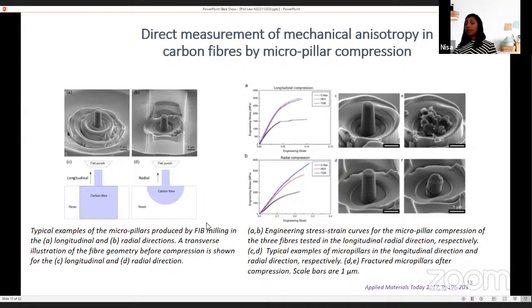So we have conducted these studies on 3 different carbon fibers with various modulus. We found that tensile stiffness was significantly higher than the compressive stiffness in all these 3 fibers. And there is a connection between the degree of crystallinity and the stiffness properties.